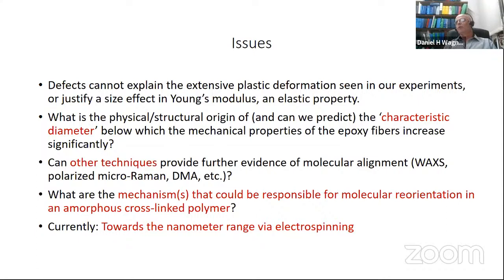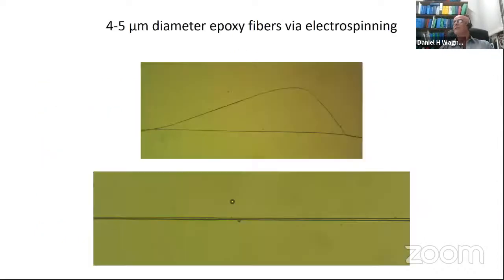And so what that will give us, it's difficult to prepare, but we have them. He's been working very hard on this, and what this will give us is the below the submicron range of diameter, and we are down to about half a micron now, so 500 nanometers at this point, using this electrospinning technique that he has developed. So that is very exciting, and we expect to have results very soon.